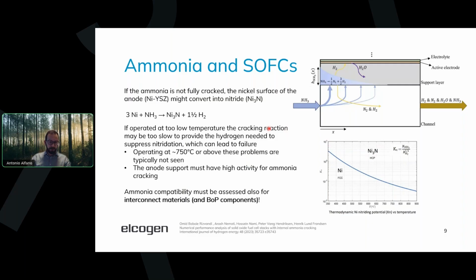The risk, which has already been discussed more than once during this webinar, is what happens if the ammonia is actually not cracked and does react with the steel components. The unit cell itself contains nickel, and that is one of the elements prone to react with ammonia and cause nitridation. And this effect, we have seen, has a dependency on temperature and also on the ratio of species between, for example, ammonia and hydrogen.